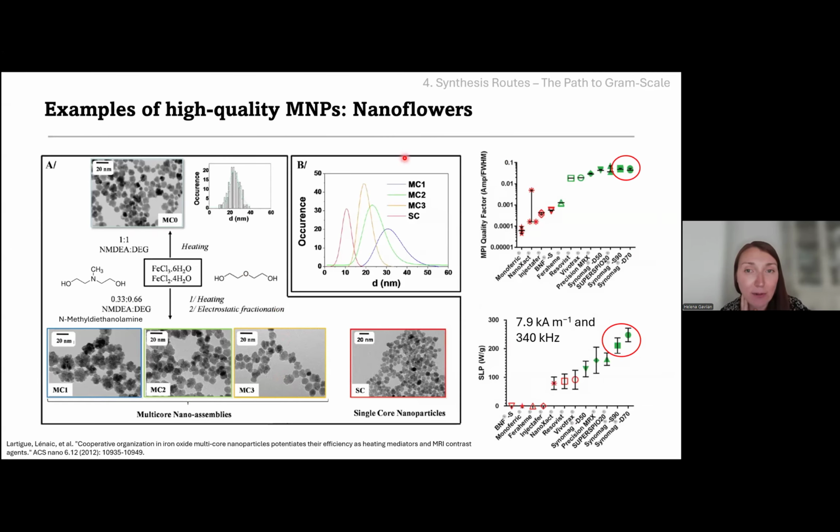The next example that I wanted to show you in this webinar are magnetic nanoflowers. Magnetic nanoflowers were produced in the past by a polyol method. So in this case, we don't have an organic high boiling point solvent. We don't have, let's say, octanol. We have a polyol like diethylene glycol. And it's very interesting because here you use a mixture of iron chloride 2 and 3, so a mixture of metal precursors.